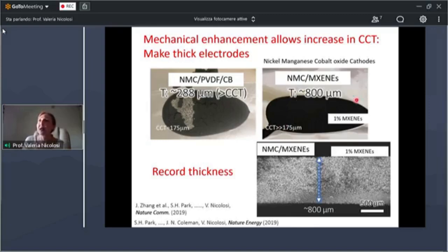For example, with MXenes, we arrived at up to 800 microns in thickness. Without MXenes, with the polymeric binder and carbon blacks, we could achieve a maximum of 288 microns. And after that, the electrodes themselves start failing. They just go above the critical crack thickness.